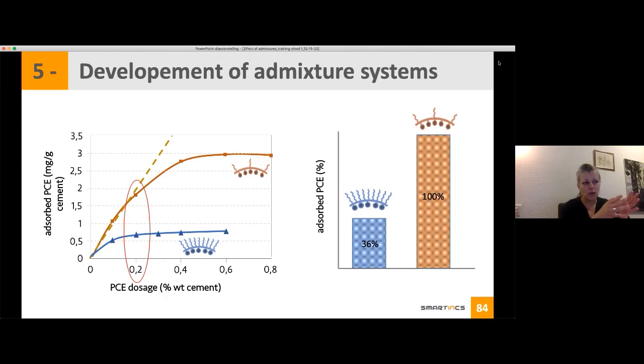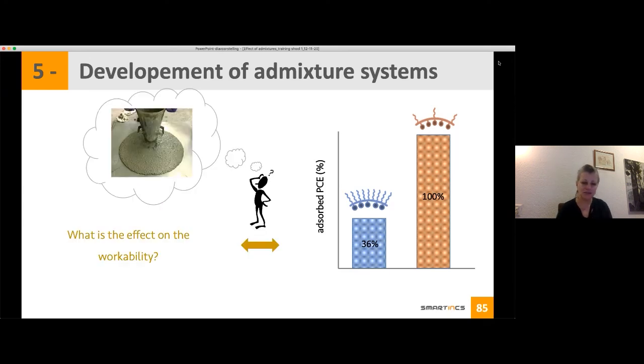For the blue one, you see that you have a big difference between what has been reacted and your dotted line, what could have reacted, and you have only 1/3 that has reacted. So you have 2/3 that is still in solution. It's nice, but I still have no indication, okay, how does it translate to my workability in my system? Because in the end, it's what you want to know.